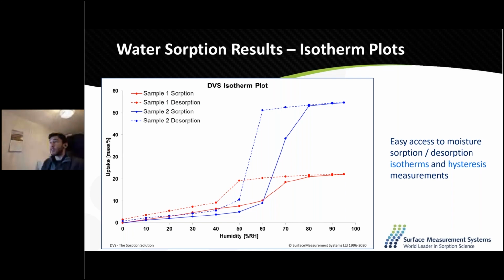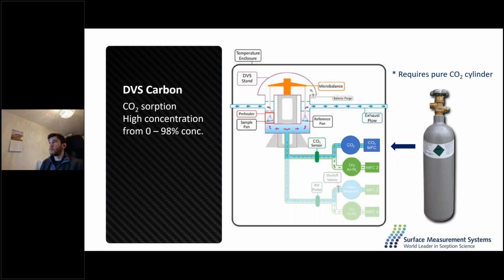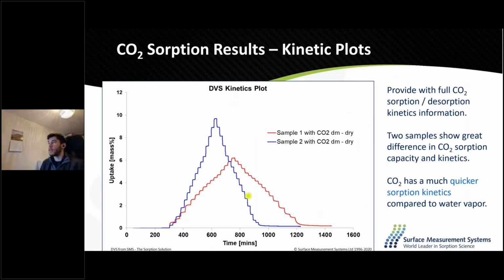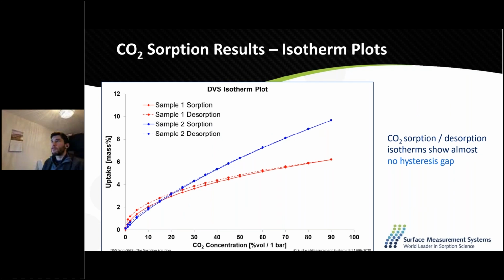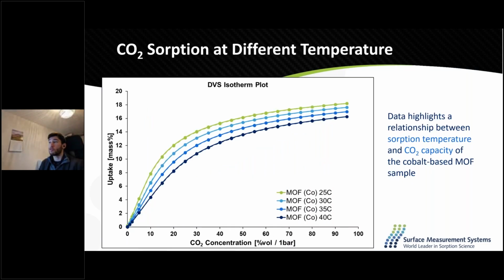This is pure CO2 adsorption, so CO2 in a carrier gas. So this would be how a CO2 isotherm looks like. We have the same sort of setup, adsorption and desorption on 2 different samples. One has quicker kinetics, the other one has a bit of a slower uptake. Then these are the resulting isotherms as a function of CO2 volume concentration. This is a CO2 isotherm at different temperatures, from 25 to 40. So this can be used to calculate, for example, the heat of adsorption.